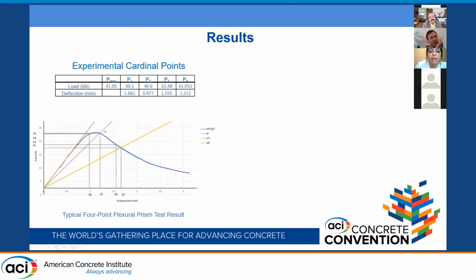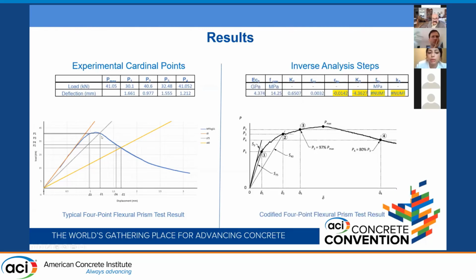Now the second sample, in here you can see that P3 is actually less than P2, and by default when P3 is less than P2 the method is not applicable, but still you can see that the 75% of the initial stiffness as well as the 40% of the initial stiffness are also located in the strain softening and not in the strain hardening region. And that's a comparison between what we are getting as a typical load deflection curve versus the codified load deflection curve, and similar results where unrealistic results are received or calculated for the ultimate portion. Here we can see some of the tested specimens.